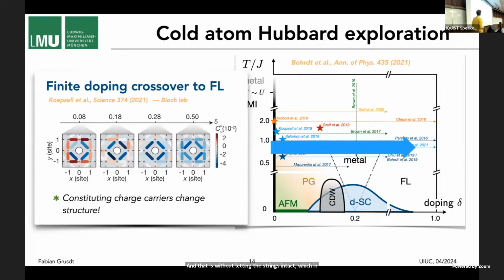All right, now we can look at this in even more detail, and this is again a project we had with Immanuel Bloch's group. They went to a little bit further dopings, slightly higher temperatures, and now they looked again at how these local spin correlations around the hole change with doping. So before I emphasized this blue diagonal bond here, and you can see if you dope, this is 50% doping now, this diagonal bond is always negative. Okay, so having this spin flip on that diagonal bond as compared to the bare antiferromagnet doesn't seem too surprising. But what they found is they looked at this straight bond here, and that ended up being positive on that side and turned into something negative if you went to higher doping.